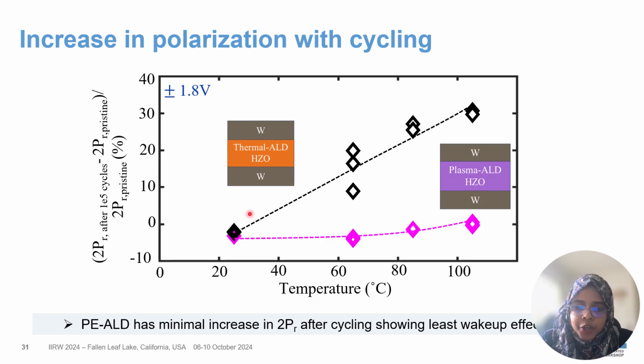Now, at room temperature, what we see is that both the devices were having similar polarization change. However, as soon as we're going to higher temperature, the plasma ALD device doesn't show any significant increase in polarization. However, if we look into the thermal ALD curve, we see that a significant increase in polarization is seen when the thermal ALD sample is used. So this means that the thermal ALD sample is having a more prominent wake-up effect compared to plasma ALD over a wide range of temperature.